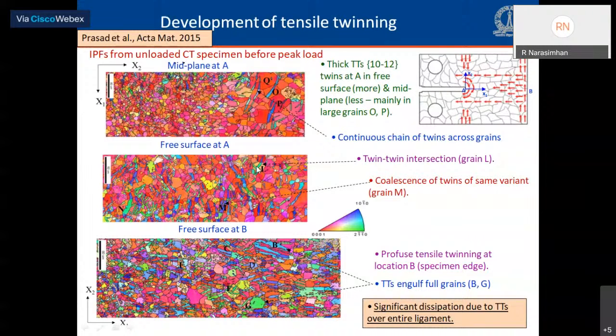Now, in all these images, all the IPF maps, we can see presence of thick extension twins, 10-12 type twins. And comparing the top IPF image with the middle one, we see more profuse twinning in the free surface compared to the midplane in this case. And that's because of the texture difference which I noted in the last slide.